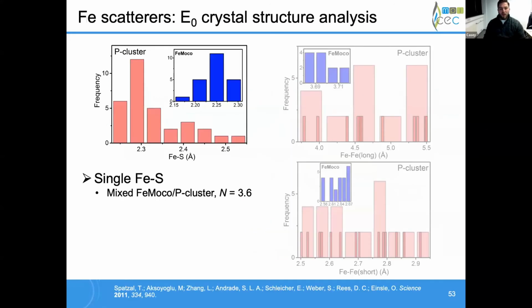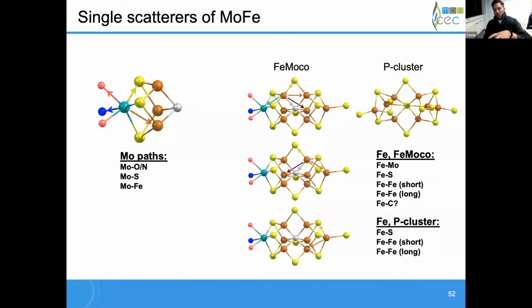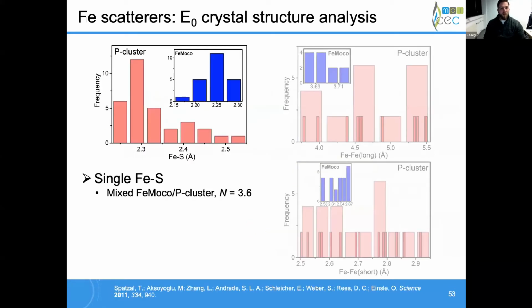And so the real question here is how we can compact and do some reduction in terms of our parameters and appropriately fit these without overfitting them. If we look at the crystal structure, we can plot some histograms of the average bond distances. And so for the iron-sulfur distance in the FeMoco cofactor, it's pretty tight. It's all within about 0.15 angstroms, and obviously deserves only one scattering path.